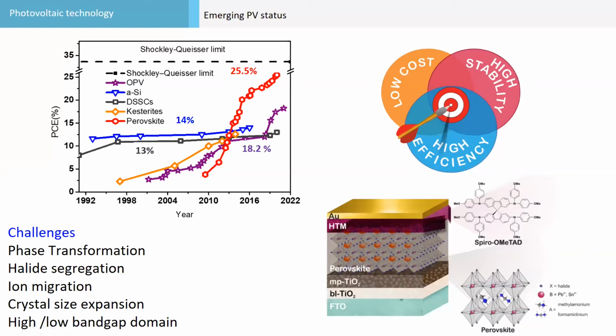There is a phase transformation. If you take methylammonium lead iodide, MAPbI3, the basic one which everybody started with, at 80 degrees it changes from one phase to another phase. Then we have halide segregation, because we get very excited when we get a high efficiency with the use of mixed perovskite. But then we learn that under the light, the halide, I will show you how, gets segregated and they form clusters of bromide and iodide. Under light, some of them also show ion migration, crystal size expansion, and high band gap and low band gap.